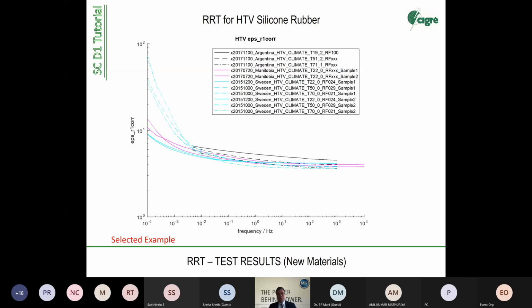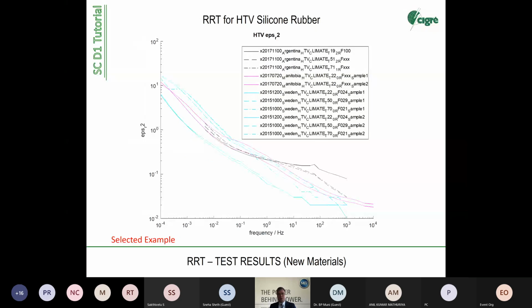Same here. It's the loss part, the imaginary part, the falling tendency. It fits perfectly with the theory. Also, what's there right here is the temperature. You see different temperatures, for example, and so you see a clear tendency in increasing the loss or the imaginary part if you're increasing the temperature. That was not a surprise, but it's confirmed here because you enable more energy levels in the material, energetic levels, that the process is more likely to happen. Arrhenius theory, it fully fits here.